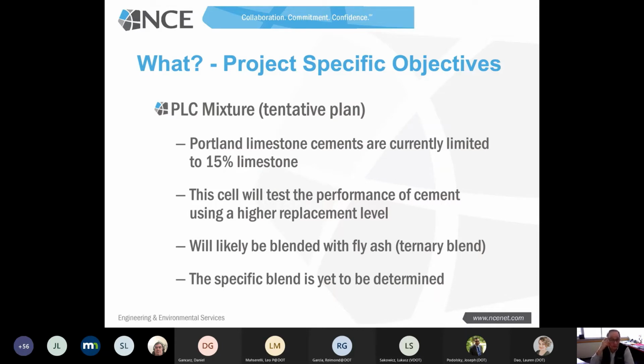The Portland limestone cement, the PLC mixture, for that mix, we're tentatively looking at probably something on the order of 25%. Currently, the standard limits the Portland limestone substitution to 15%, but we want to push it out farther. So we're going to be looking at 25% as the replacement level. Almost certainly, we're going to blend this 25% PLC with a fly ash to produce a ternary blend. And that is because research has been conducted by Jason Weiss at Oregon State. A number of other people have shown that there's a synergy between the fly ash and the limestone replacement that really helps to allow for this higher replacement level and still achieve the same level of performance. But the specific blend is yet to be determined, and we are working through some of these details yet.